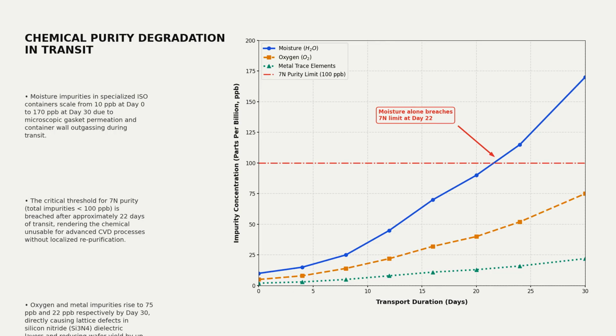Over time, microscopic gasket permeation and container wall outgassing contaminate the cargo. Moisture levels inside the ISO containers rise from 10 parts per billion at day 0 to 170 parts per billion at day 30. The critical threshold for 7N purity is breached after approximately 22 days of transit. Beyond this point, the gas becomes unusable for advanced chemical vapor deposition.